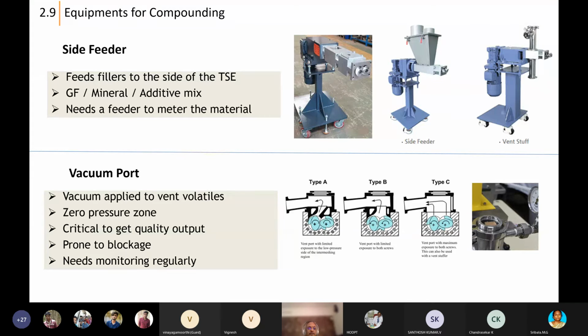I talked about the vacuum port. So vacuum is applied to the vent to remove the volatiles. It's a zero pressure zone, which is very critical to get quality output. If you process nylon and take out the material without removing the volatiles, you will see a very good granule. But if you take these granules into injection molding, you will find a lot of voids coming in the molded part because volatiles are still inside the polymer matrix. So a good material needs all the volatiles to be removed from the matrix of the polymer. That's why a vacuum port is given in the extruder.